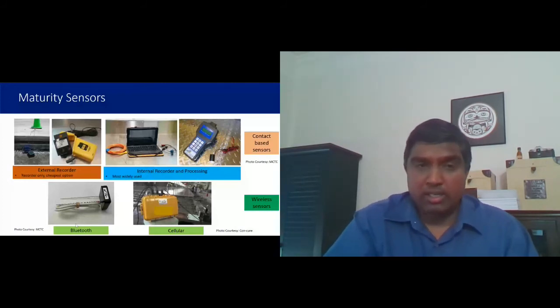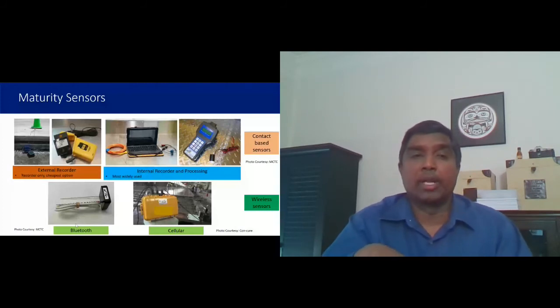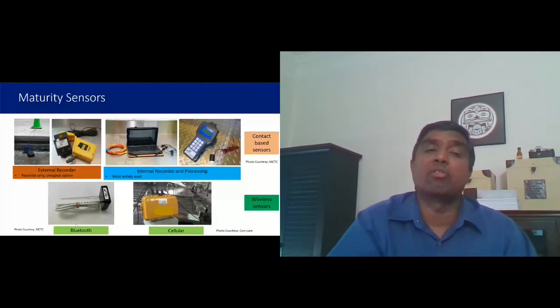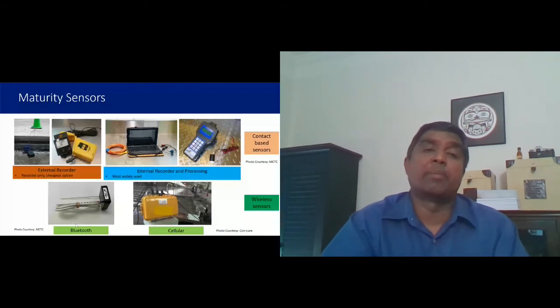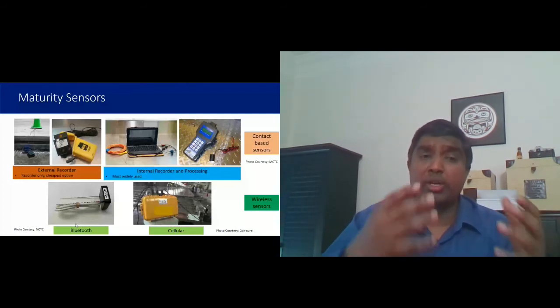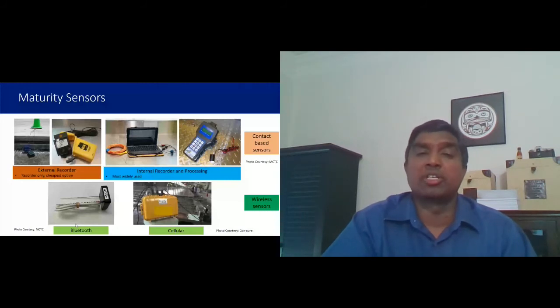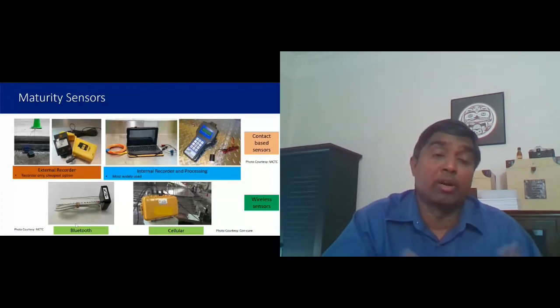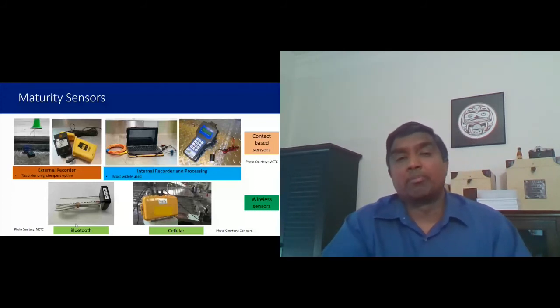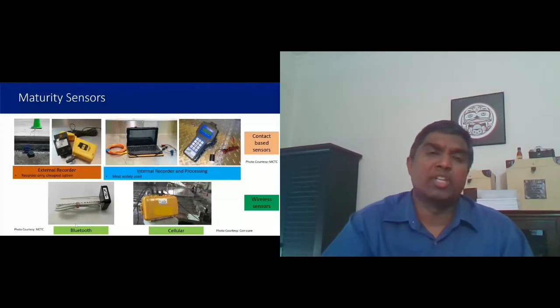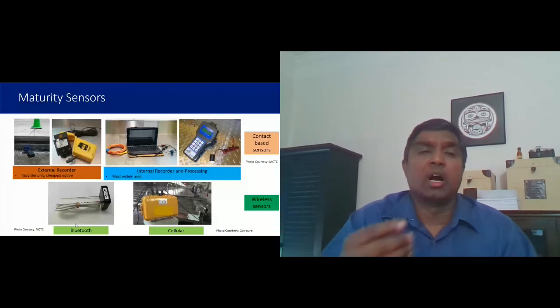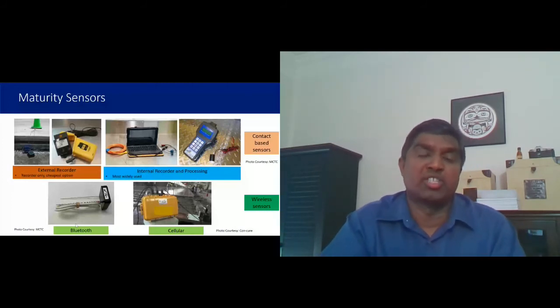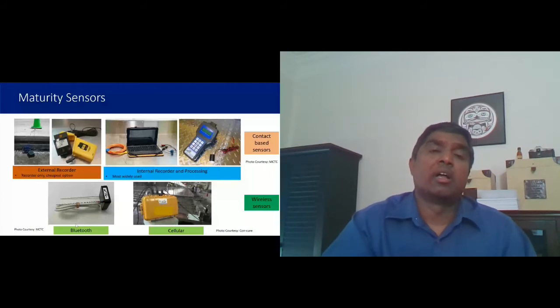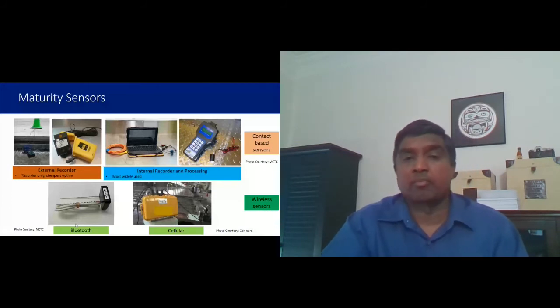With these sensors, basically they measure time and temperature, but the actual recorder itself is left at the paving site. So it's actually visible. The problem with this approach is that sometimes the sensors get run over by construction equipment, or people tend to steal them. Nobody uses these anymore. The good part is they're very inexpensive. You would only be losing a piece of wire every time you use these sensors.